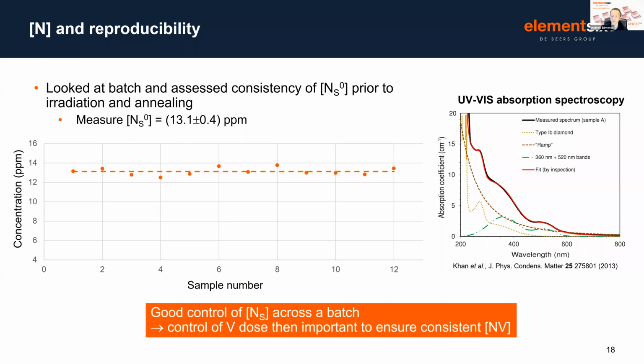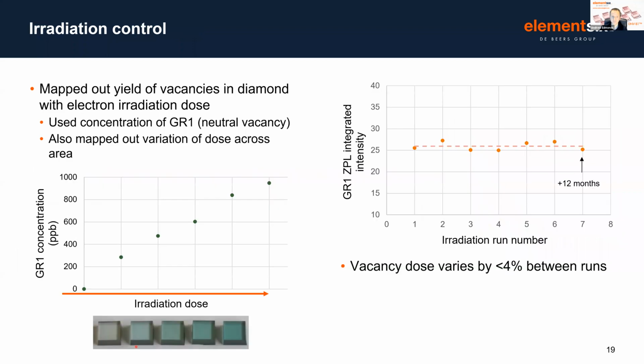But then what we had to be concerned with was, did we have good control of vacancies that we were dosing via electron irradiation that would ultimately give us a consistent NV concentration in the final material? So we looked at the control during electron irradiation. And to begin with, we simply mapped out the amount of GR1, as it's known, which is just an isolated vacancy defect in diamond, as a function of our irradiation dose. And this just corresponds to irradiating the diamond sample for a longer time. And in the case of increasing GR1 concentrations, what happens is our diamond becomes increasingly green. So we could then use this map to choose a suitable level of irradiation to create the desired level of NV centers in our material.